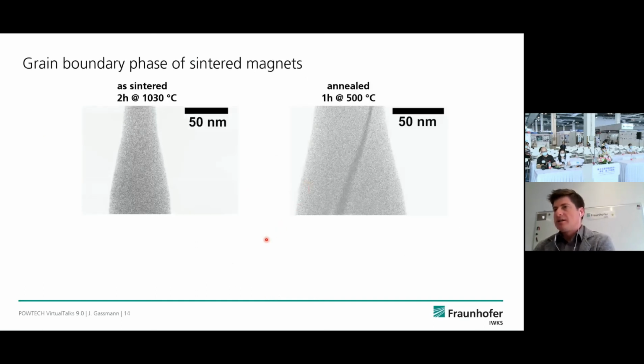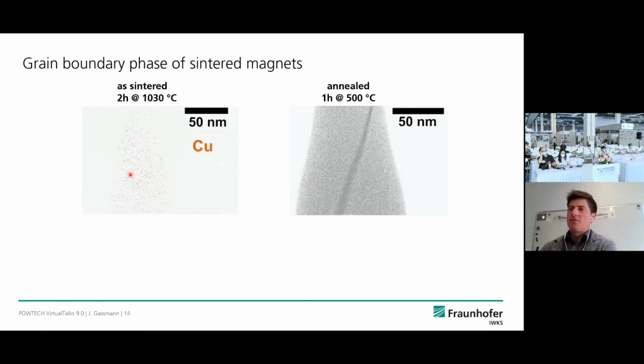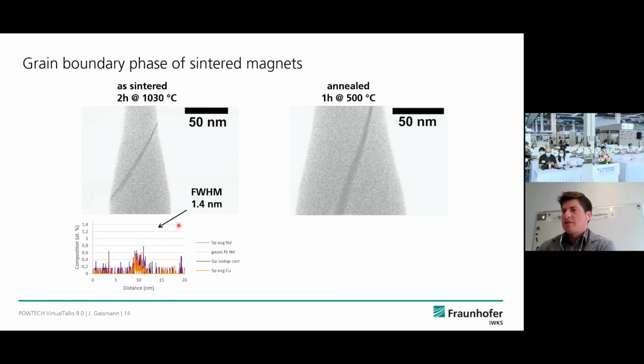So if one checks that directly after sintering, here we see the signal of neodymium, the signal of copper. We see the grain boundary phase right here in the middle, and also the signal of the gallium element. So when we check that, we see that we have an intergranular phase size of about 1.4 nanometer, and the gallium is somehow distributed Gaussian type after the sintering.